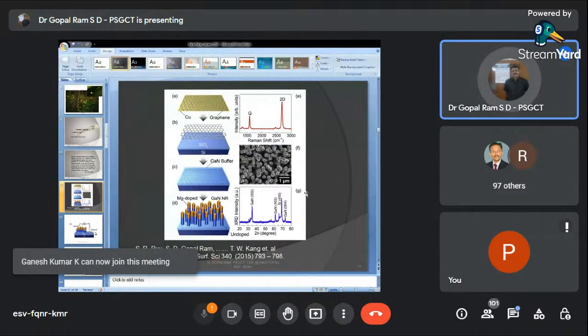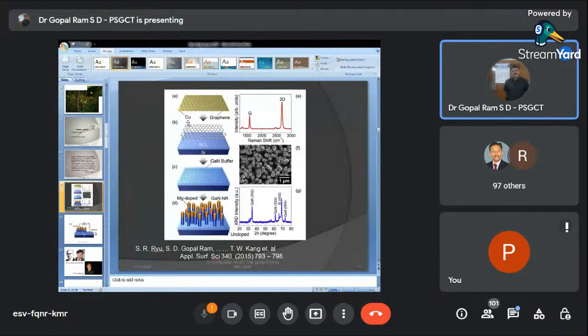As you can see in our work, what we have done is we have used this graphene layer. This graphene layer is produced by the regular chemical vapor deposition method. So you can see we introduce a copper plate into a CVD.